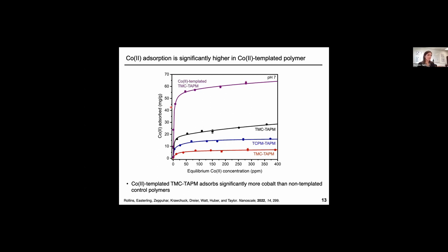Cobalt 2 versus manganese 2 versus nickel 2 in aqueous solution are going to be really similar, with very similar ionic radii and charge density. But this is the type of ultimate goal that we're going for. So in order to improve the performance further, we are continuing to work on engineering a more selective binding site and improving rigidity and decreasing swelling in these materials so that we could ultimately be able to selectively capture one transition metal cation.